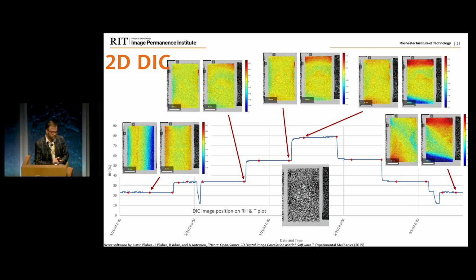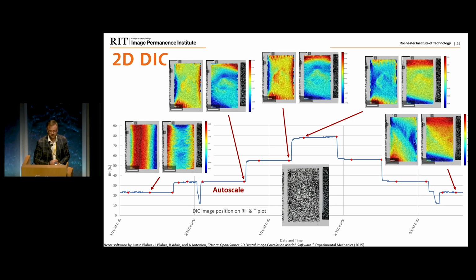The numbers are in the ballpark of the strain rates we've seen in the DMA. They don't match ideally, but we're going to get there. What is more interesting, though, is that if you scale those images to the local maximum and minimum for each particular image, you can actually start investigating how the influence of this local cross is acting, and how the paint actually does expand more.